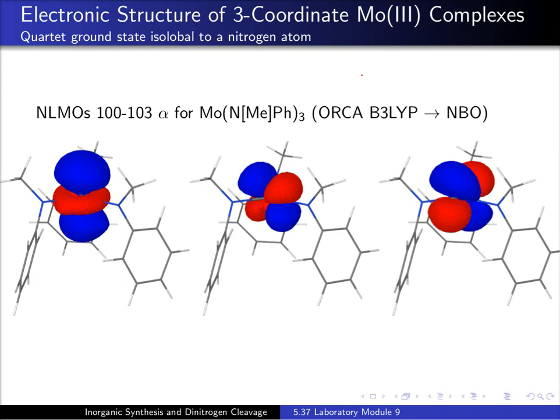So having mentioned that we've got 3 non-bonding d electrons in this system, let me just point out that these are in orbitals that, from an electronic structure calculation on a model system where we have just a methyl group and a phenyl group on the amide nitrogens as the substituents, we see here that if our z-axis is pointing up this way, the orbital here containing one of the non-bonding d electrons is the dz squared orbital, and then we have one electron in dxz and one electron in dyz.